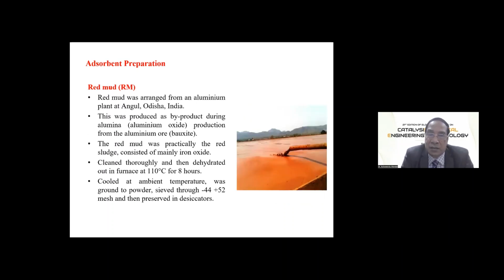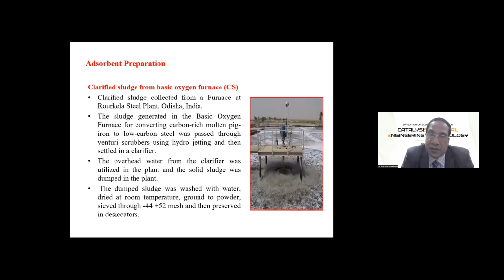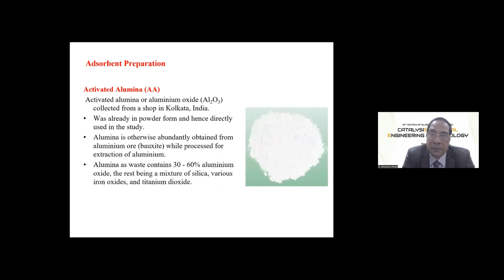Then this is red mud, collected from the aluminum plant where the bauxite is being treated for getting the aluminium. Then this is clarified sludge from the basic oxygen furnace. This is mainly from the steel industry, and there we will be producing low-carbon steel from the carbon-rich molten pig iron. There, this sludge is generated that we have taken. And finally, the activated alumina. This is also from the aluminum plant, and is mainly having aluminum oxide as well as some quantum of silica, ferrous iron oxide and titanium oxide.